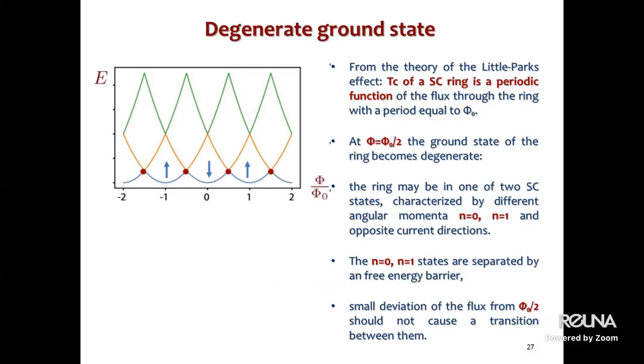Exactly at half flux quantum, the ground state of the ring becomes degenerate. So we have n equal to 1 and n equal to 0, degenerate at this point. The ring may be in one of two superconducting states, either n equal to 0 or n equal to 1, with opposite current direction. So n equal to 0 in this situation is counterclockwise, n equal to 1 is clockwise. These states are separated by a free energy barrier, and a small deviation of the flux from half quantum should not actually cause a transition between them.